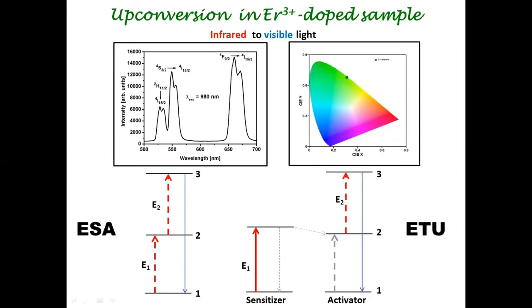So we can convert infrared to visible light by doping with erbium. You shine 980 nanometers, and the light emitted is green light. So we convert longer wavelength light to shorter wavelength light by this process, excited state absorption. Two photons are involved. One photon takes the erbium ion from level 1 to 2, and then another photon of the same energy takes the erbium ion from level 2 to 3. Then the erbium ions come to the lower energy levels, and in that process they emit green light. So this is the process of excited state absorption occurring in upconversion involving erbium ions.